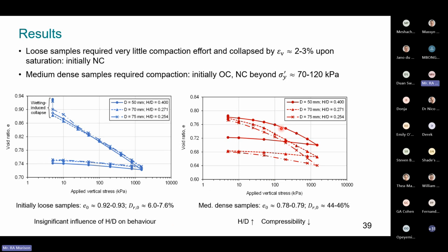Looking at our medium dense sand, once we've moved into the normally consolidated regime, we're looking at three very different compression curves. So as we increased our aspect ratio or decreased our diameter relative to the height, the compressibility decreased, which means that we're under-measuring compression because of our boundary effects.